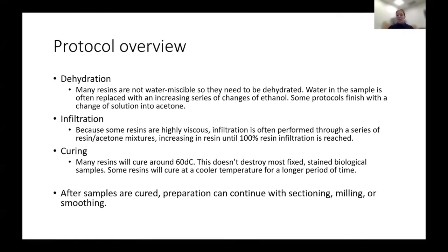Dehydration, if necessary. Infiltration, whether or not dehydration is necessary, is almost always necessary. Unless you're working with a solid piece and you don't care about the resin getting inside the sample, and you only care about creating structural stability around that sample, then you don't even need to infiltrate. You just drop your sample in some liquid resin and cure it. And the last step is curing. That creates a monolithic hard block of resin.